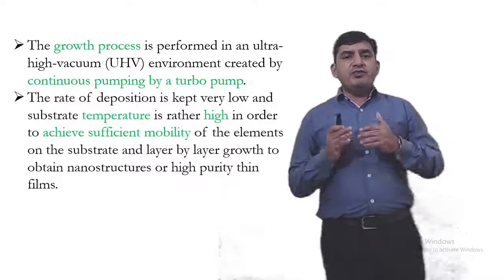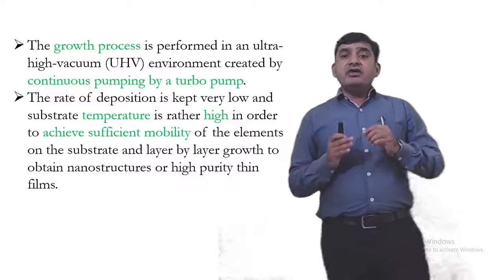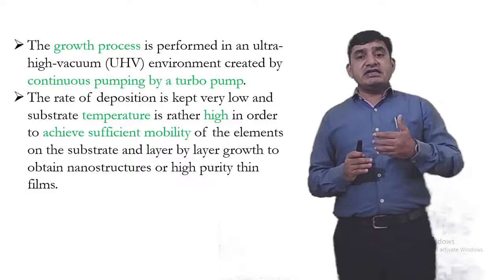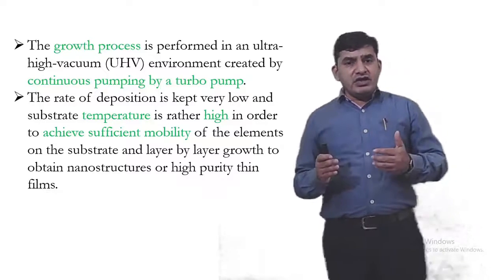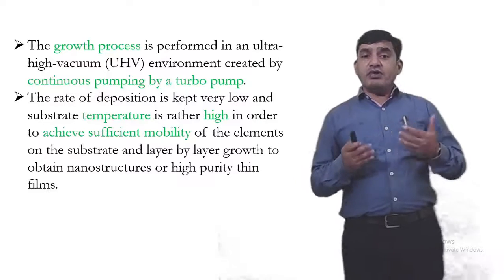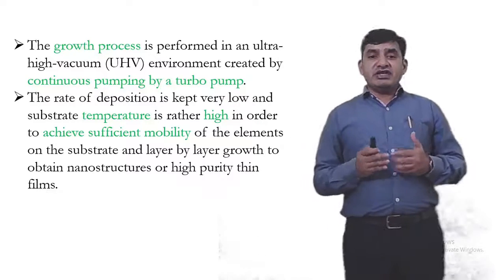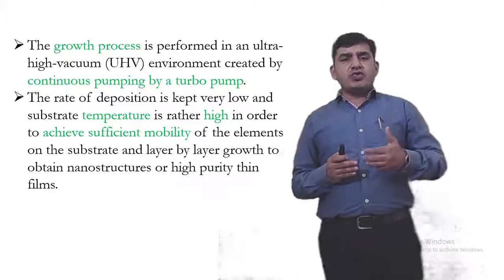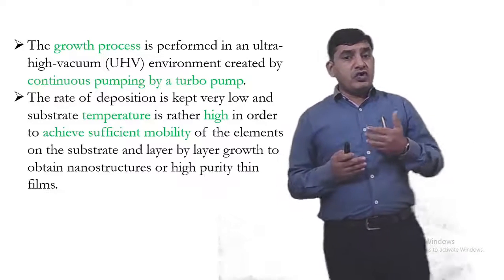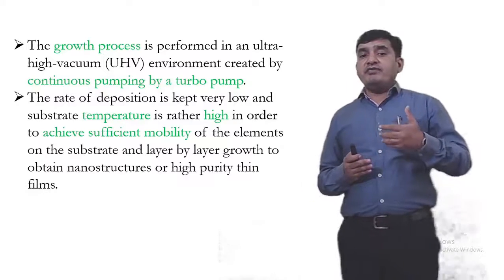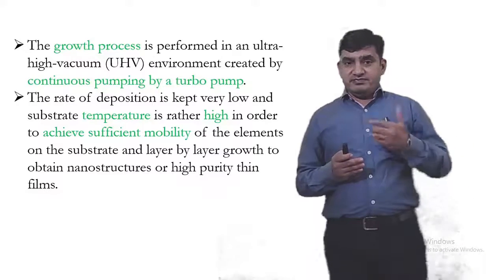The rate of deposition is kept very low and the substrate temperature is rather high, in order to achieve sufficient mobility of the elements on the substrate and then layer by layer growth to obtain a nanostructure or high purity thin film.